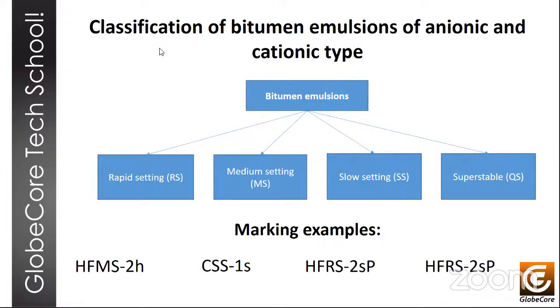For example, if we have an emulsion called HFRS2SP, that stands for anionic, rapid setting, high flotation emulsion of low viscosity, based on thin polymer modified bitumen.